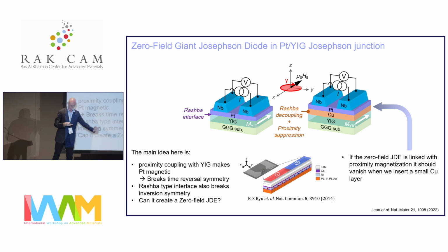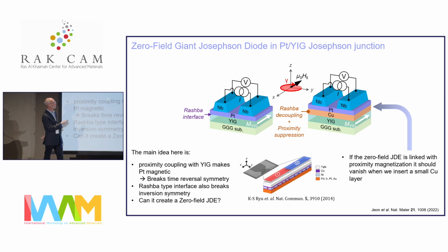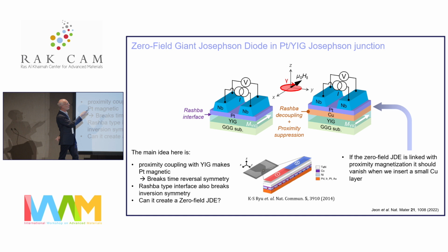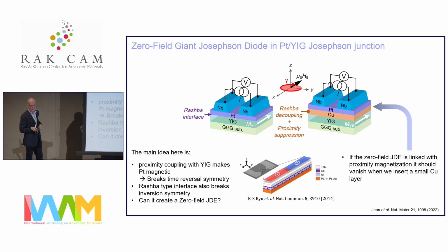just as for the nickel ditelluride, we build a Josephson junction here using niobium layers. And now we flow supercurrent from one niobium to the other through platinum. Well, the platinum becomes superconducting by proximity, and the platinum is magnetic by proximity to the lower substrate. Through two proximity-induced effects, we can build a Josephson diode.